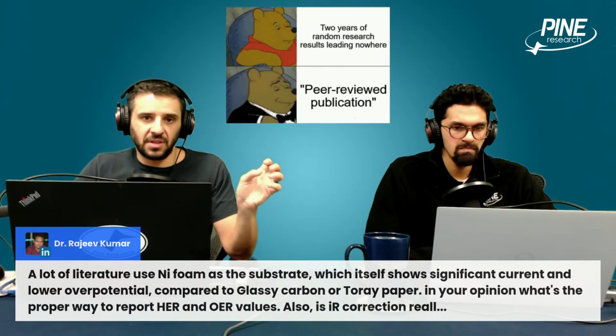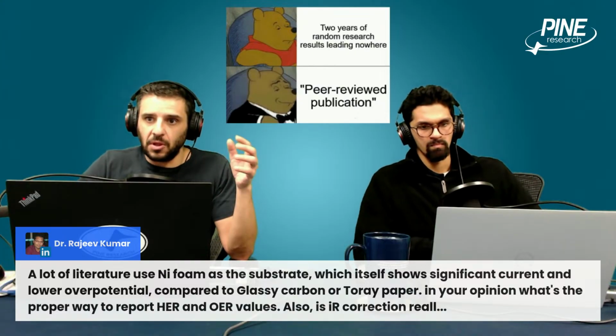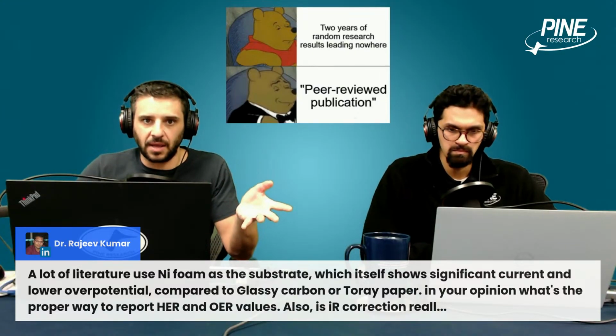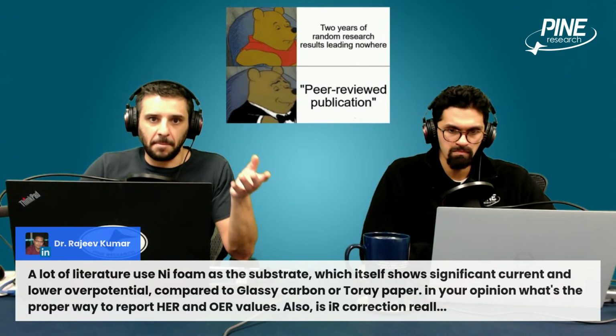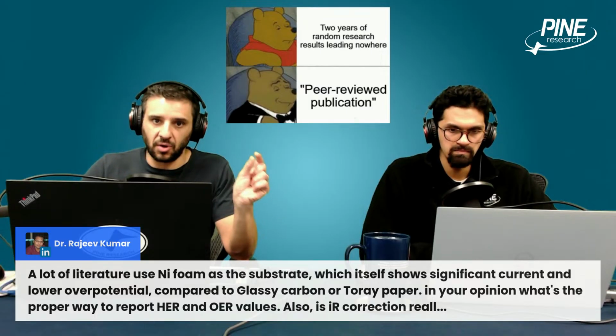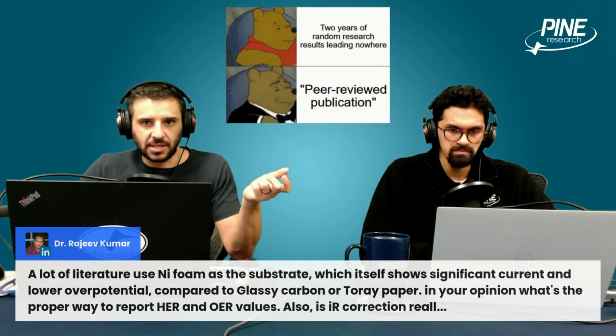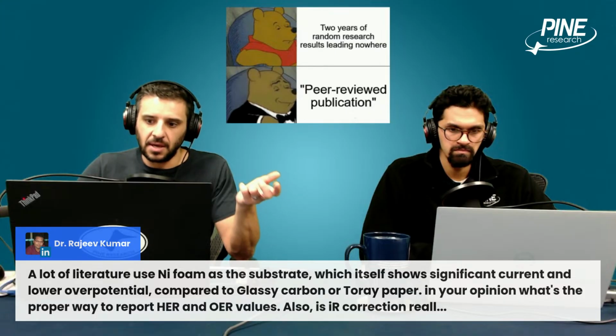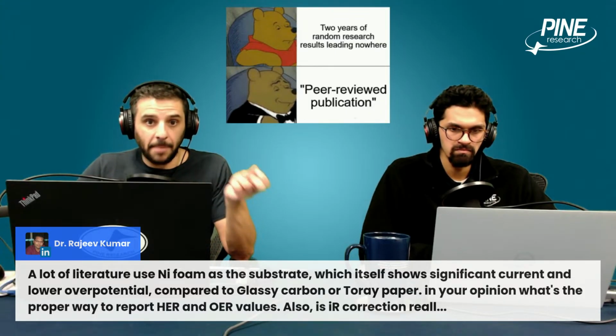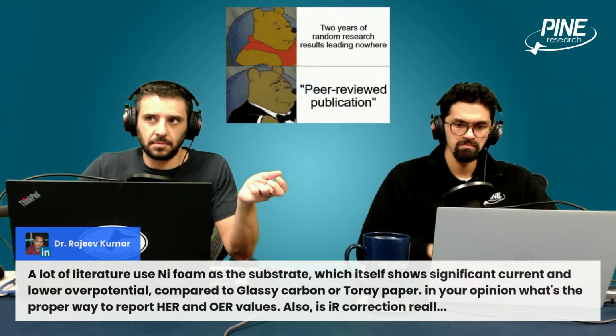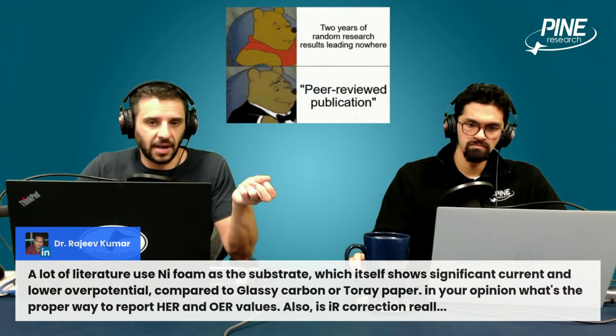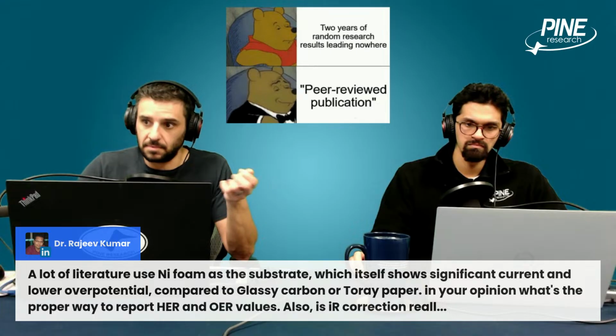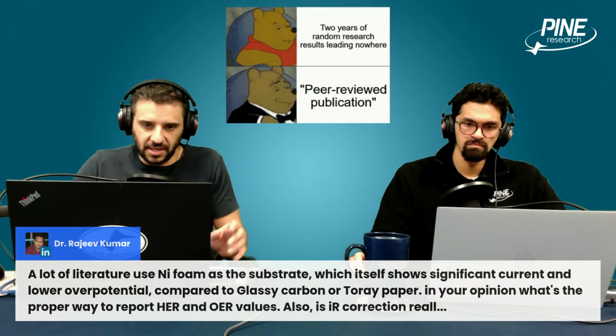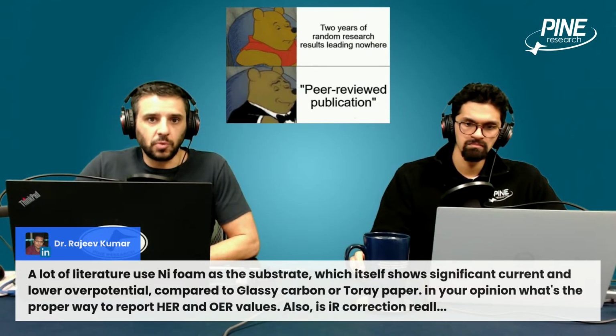dwarfs the activity of the nickel, so even though the nickel is participating, pick something with a much better overpotential, like smaller overpotential, and a much greater activity, such that you can effectively neglect the contribution of the nickel itself. Right now, if that isn't possible, and it may not be, because nickel, like I said, is not the best, but it's not insignificant in terms of it will do the OER and the HER and things like that. The other is to make sure, and this is a really difficult one, make sure the nickel